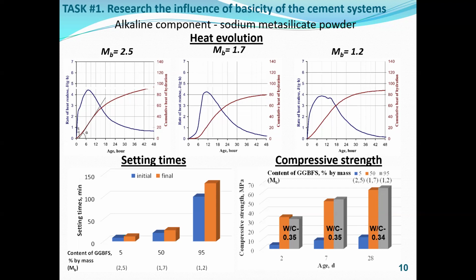Alkali-activated cement system containing 5% of slag is characterized by extremely quick setting times and low strength, which correlated with the data concerning the problem of its application. Increase in slag content in the cement system from 5 up to 95% is accompanied by an increase in initial setting times from 8 up to 100 minutes and final setting times from 11 up to 130 minutes. The obtained results correlate well with the data of the thermokinetic analysis.